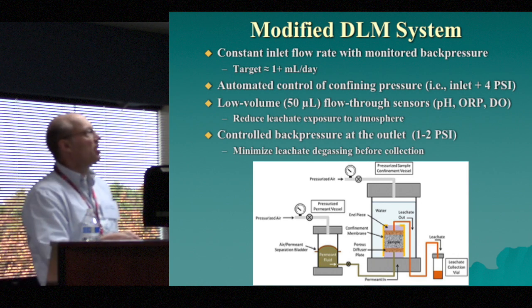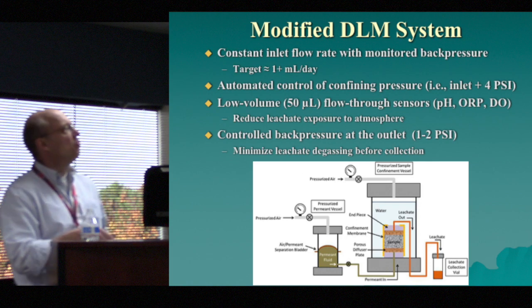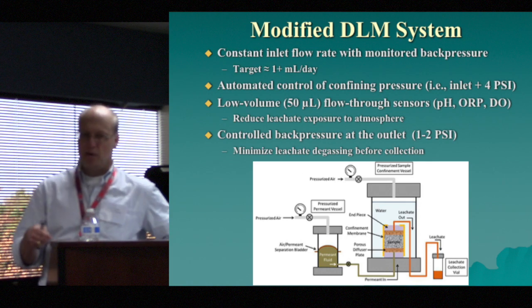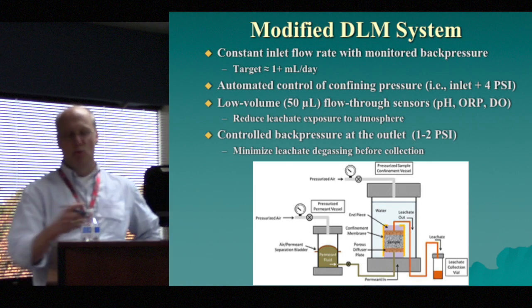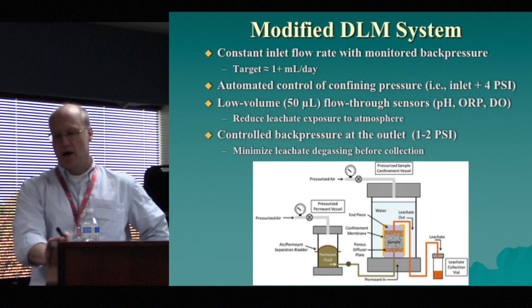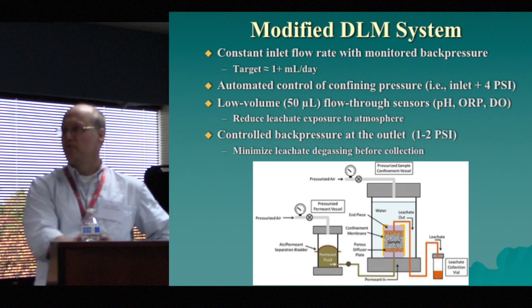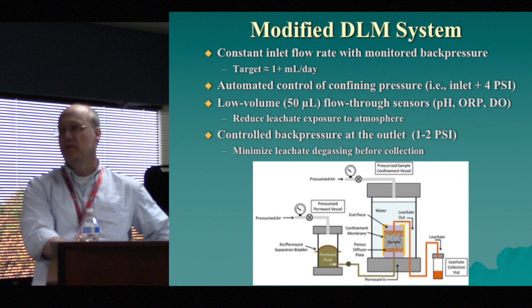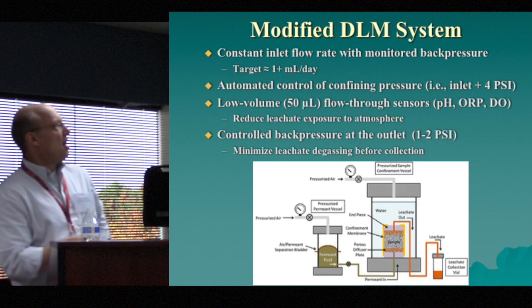And so what we're targeting is a flow rate of about 1 milliliter per day. And what we think is we can actually do twice that and see if we can see a residence time effect in these types of experiments.